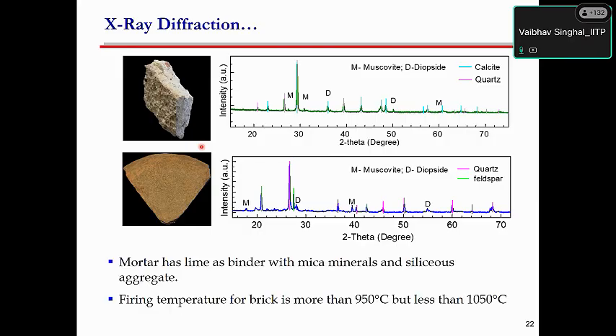structures. So as I said, we found out the mortar which is used commonly for the render for the plaster is a lime mortar consisting only of the lime as a binder with some mica mineral, and the aggregates are primarily the siliceous aggregates. The firing temperature has been found for the bricks to be more than 950 but less than 1050. So it was in the range of 950 to 1050 degrees centigrade.